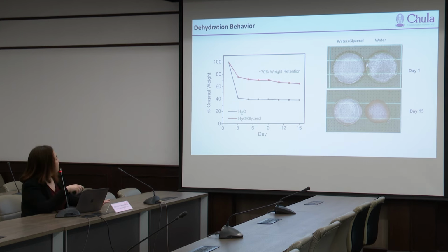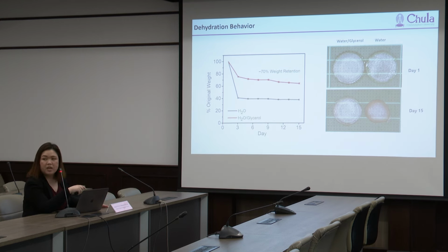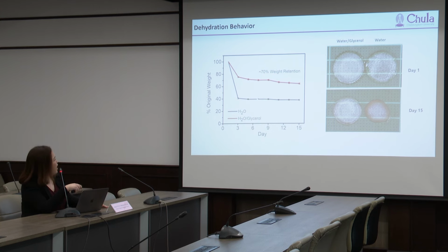So if you look at this graph, you can see that the mixture that has glycerol has 70% weight retention, compared to the one without glycerol, which has only 48% retention. And if you look at the picture here, you can see that when we have the glycerol in the mixture, you can still see the hydrogel here, right?